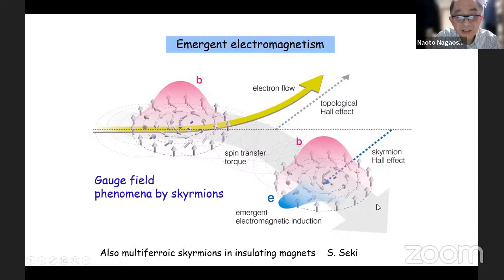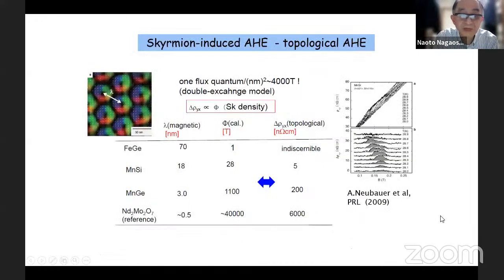And the motion of a skyrmion leads to the B dot, because the B is moving, right? And then the B dot leads to the small e. So this skyrmion Hall effect and the emergent electromagnetic induction is observed in skyrmion systems. So this is a topological Hall effect, and the size of the skyrmion is related to the flux density, and the smaller skyrmion leads to the larger flux, and then the larger Hall response. Namely, this is a topological Hall effect for each material. And only in this skyrmion phase do you have some additional Hall signal. So this is identified as a topological Hall effect coming from the skyrmion flux density.